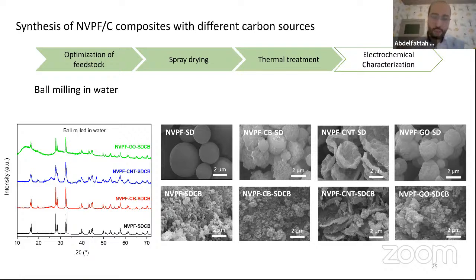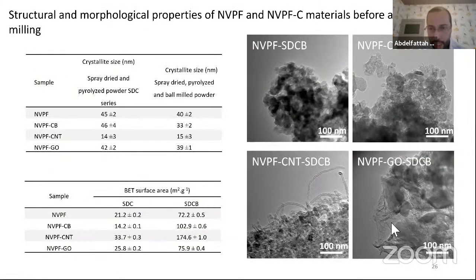in using 250 RPM. We can see that the morphology changed after grinding for all materials, and the one which is different is the one with carbon nanotubes, because carbon nanotubes have very rigid and good mechanical properties, which makes the grinding difficult. Here are the TEM images in order to see the different carbon sources, how they are mixed with the NVPF active cathode material.